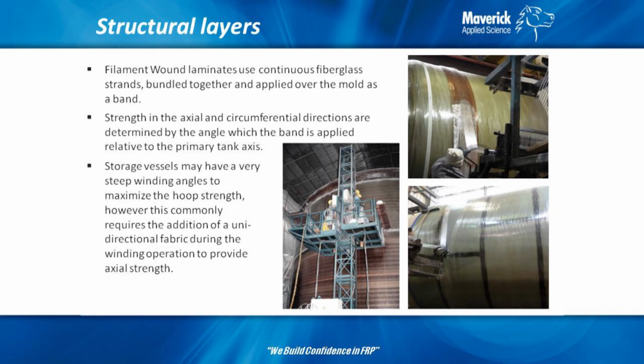Filament winding is a band of those single end rovings packaged together, run through a resin bath over here, and comes off wet. As that wet band is wrapped around, you get strength in different directions. You see this has angle to it, so maybe a 70-degree wind angle, which gives you some axial strength, but primarily circumferential strength. On a hoop wound vessel, you're getting primarily circumferential strength, and they'll put in unidirectional glass typically to give any axial strength they need.